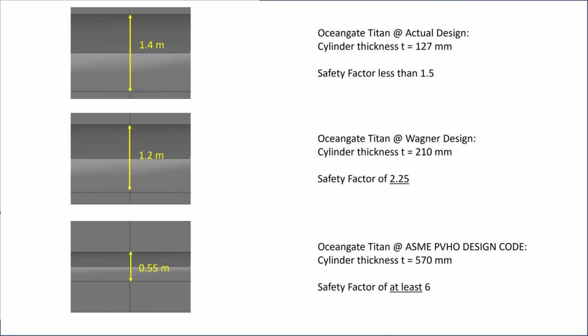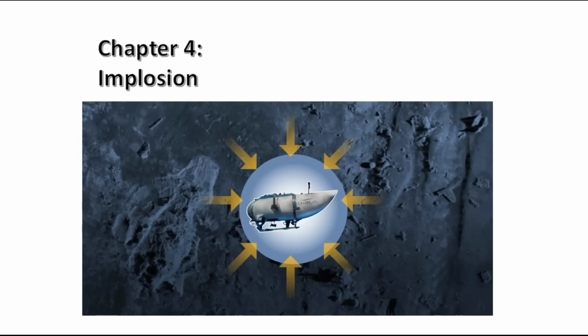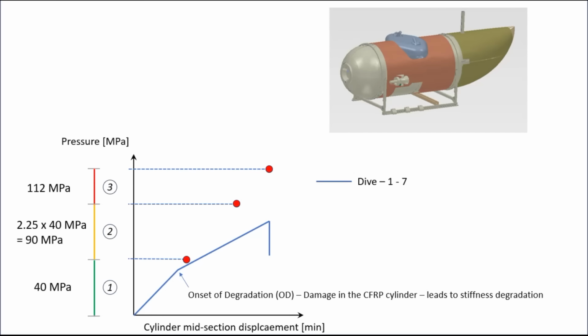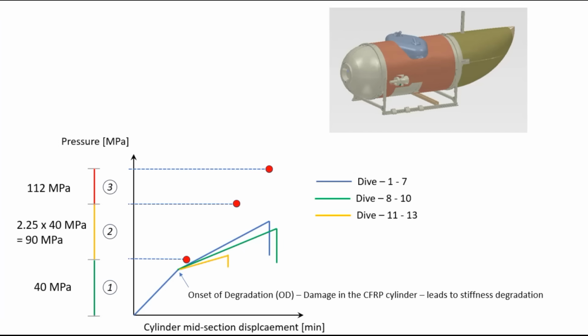As we have heard, the ASME design codes require a safety factor of 6, which would lead to a much thicker CFRP cylinder than the one the Titan had. The most likely cause for the implosion of the Titan was cycle fatigue damage. That means that over time, damage accumulated in the CFRP cylinder from each dive, which led to the final failure of the submersible.